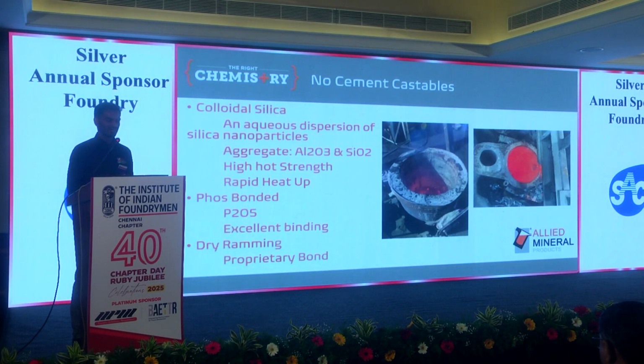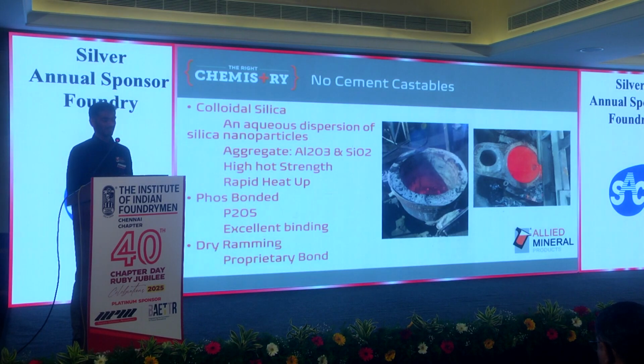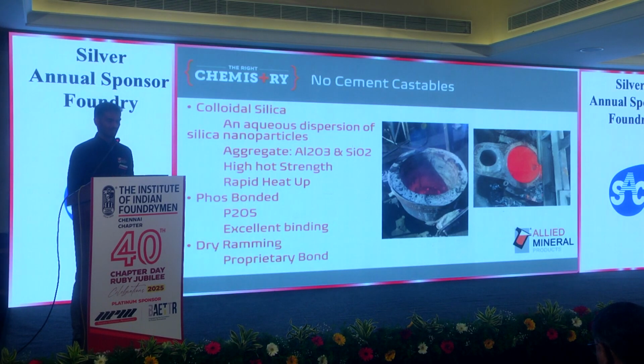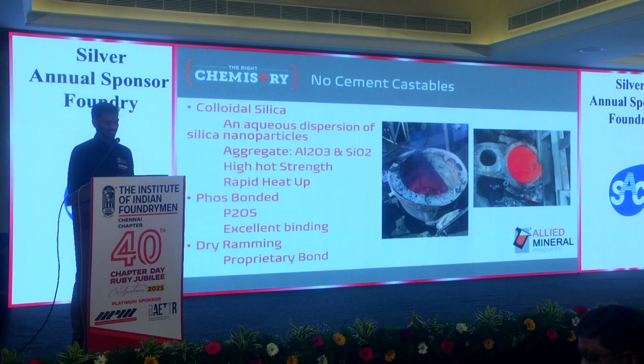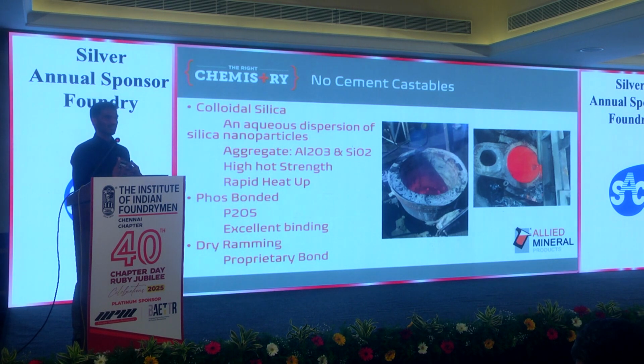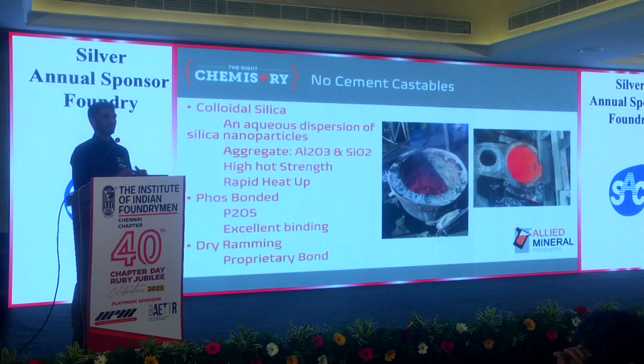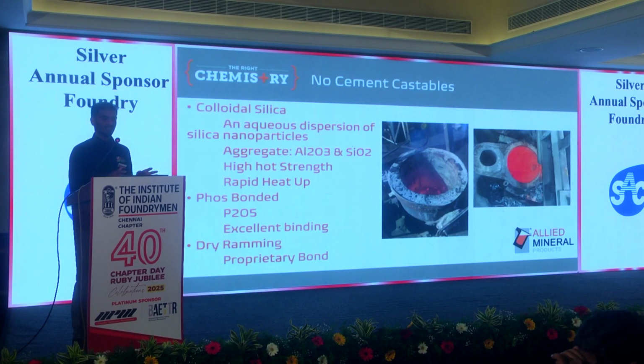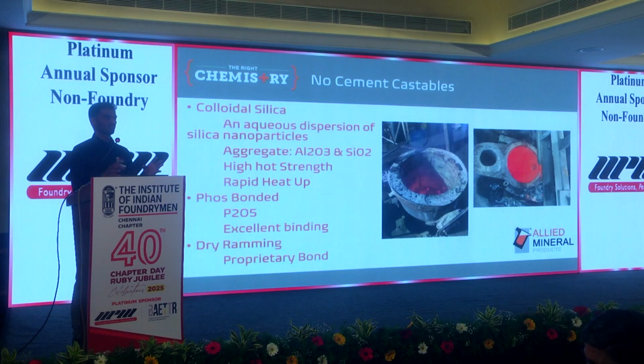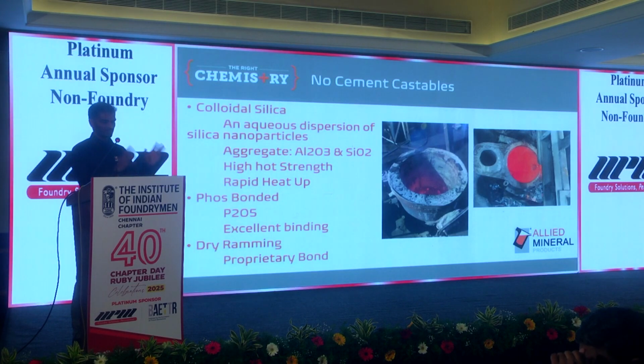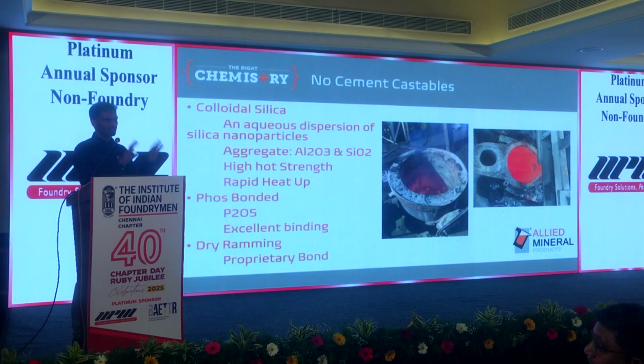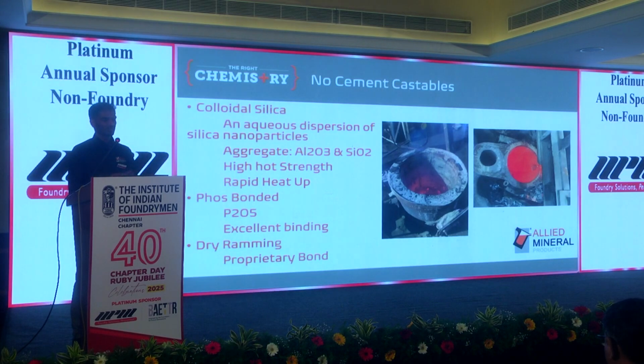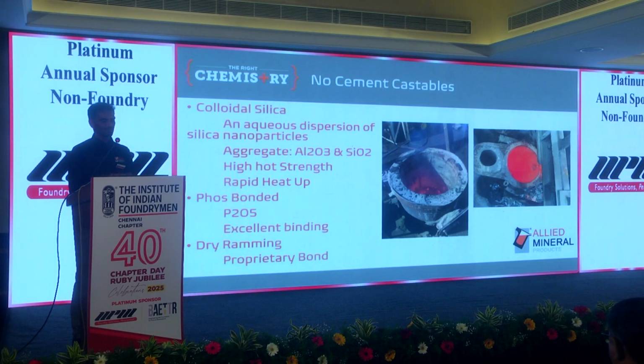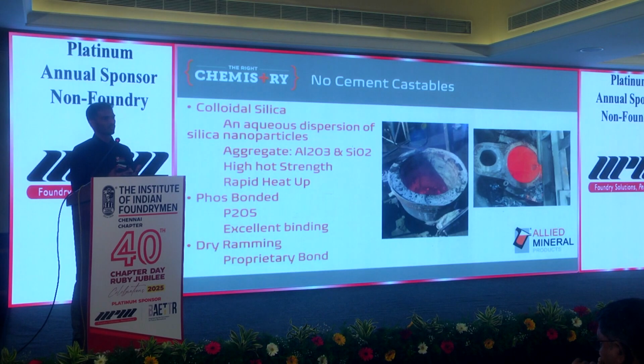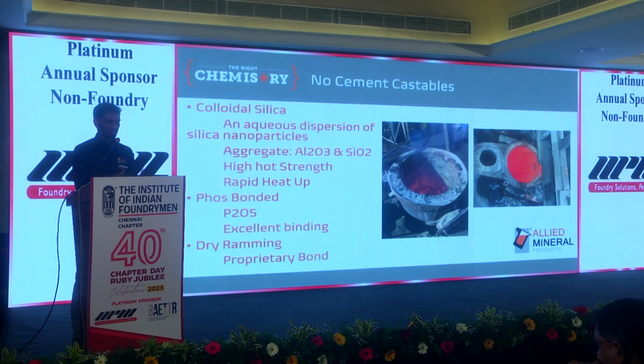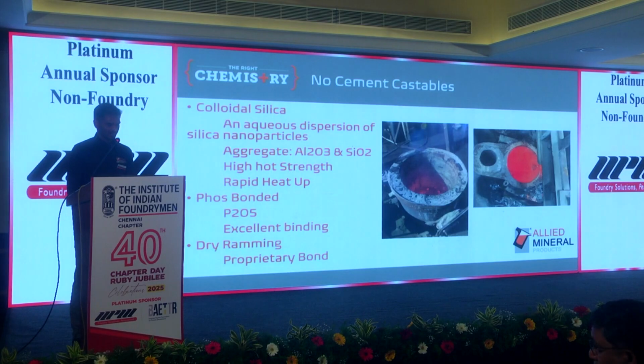And then we also have phos bonded castables and phos bonded ramming masses. And we also have dry ramming mass, which is completely non-wet. It's completely dry. You have to do it like a coreless furnace lining. It does not take so much time. If you have a vibrating table, you can set the form, put the refractory, vibrate it and it settles. Then you light it with a wooden torch or wood planks, and within 15-20 minutes or a maximum of 1 hour, your ladle will be ready. So this is the advantage with the dry ramming mass.